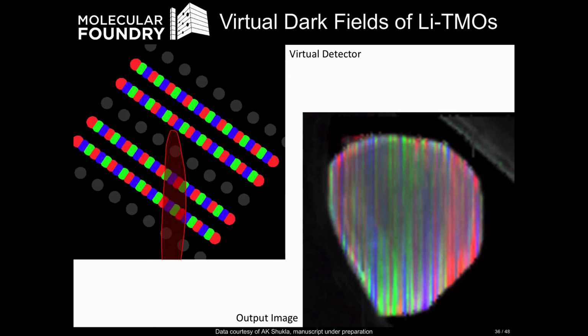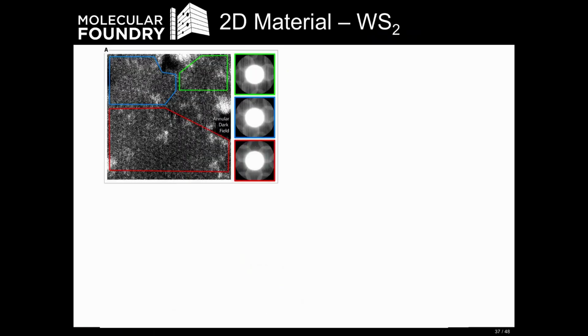And then finally, the last virtual dark field I want to show is a more challenging experiment. This is that tungsten disulfide data set I showed in that big overarching image earlier in the talk. And once again, in blue, green, and red, I've circled a bunch of the probe positions and shown the diffraction patterns. They're quite similar to each other, but the slight differences between the intensity of the disks and the overlap region can be used to tell the difference between the stacking sequences, or whether it's single layer, zero layer, two layer, three layer, et cetera. And so what I want to show in this data set is forming some complex virtual dark field images.